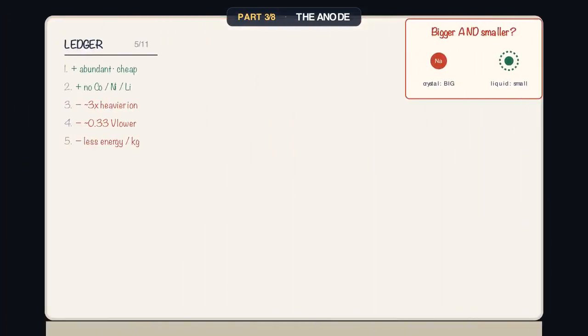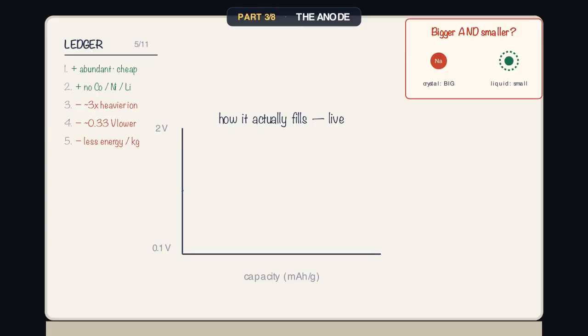Let's draw how it actually fills live. Voltage down, capacity across. First, a sloping stretch from about 2 volts down to 1/10 of a volt. Here sodium is adsorbing onto surface defects and edges. Then, a long flat plateau below 1/10 of a volt. Sodium packing into those closed pores as clusters of almost metallic sodium, and this plateau holds most of the charge. Optimized hard carbon reaches 300 to 350 milliamp-hours per gram.